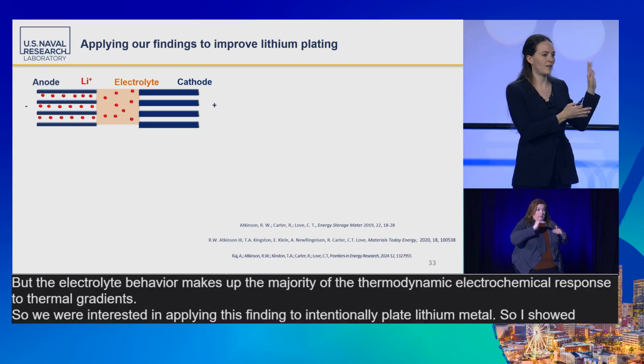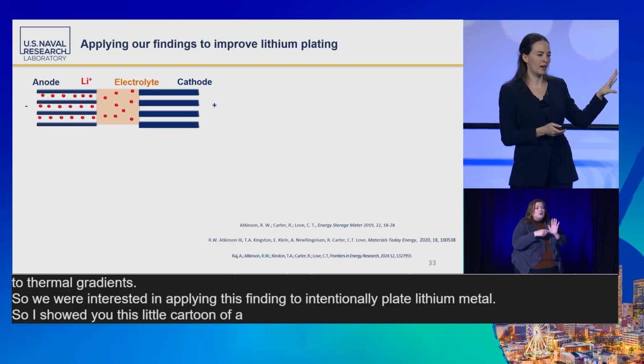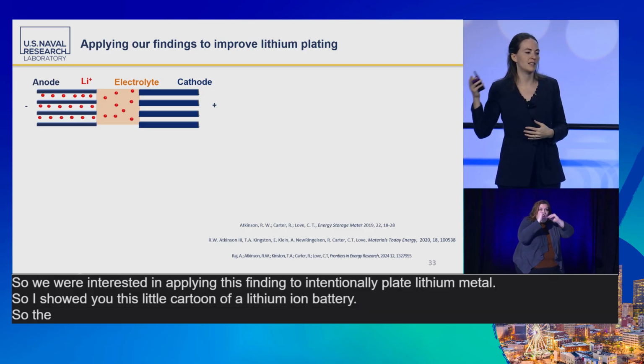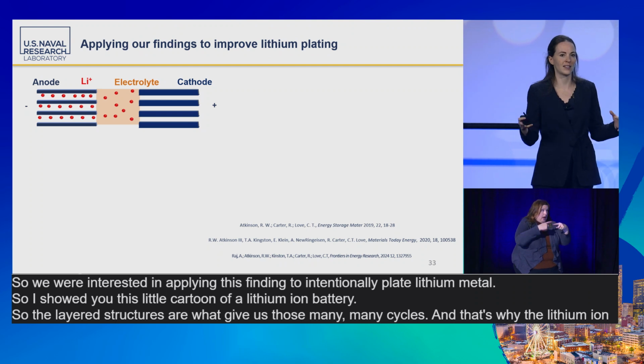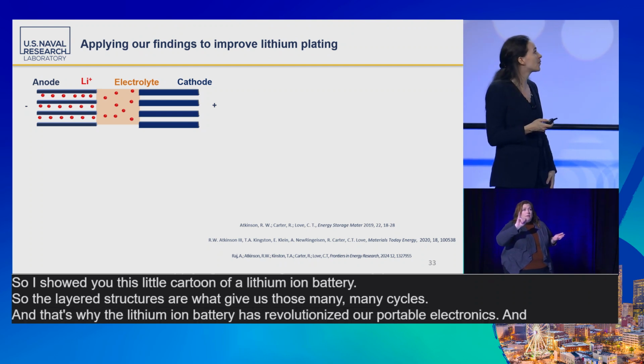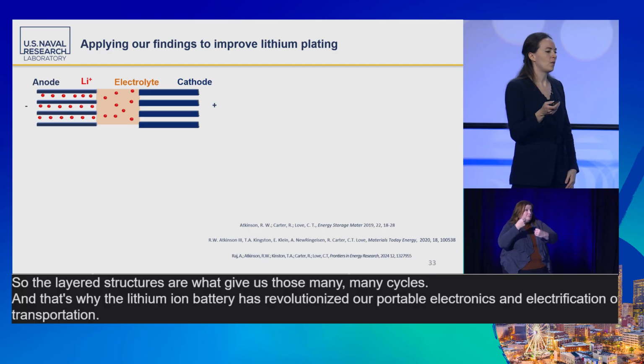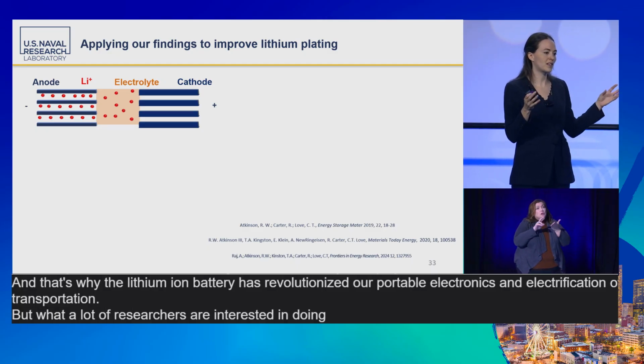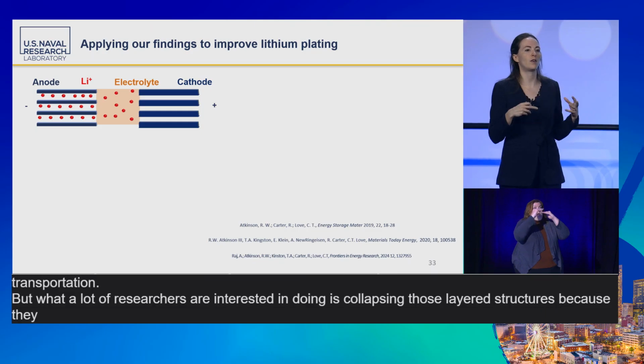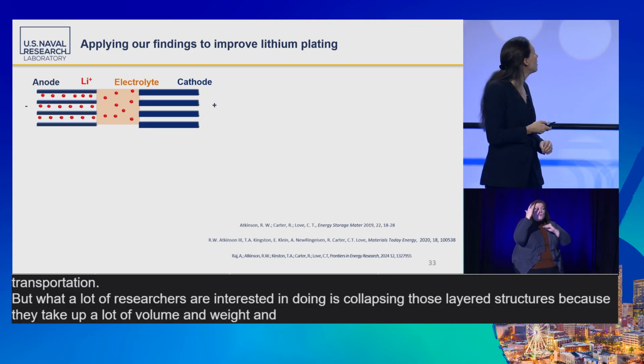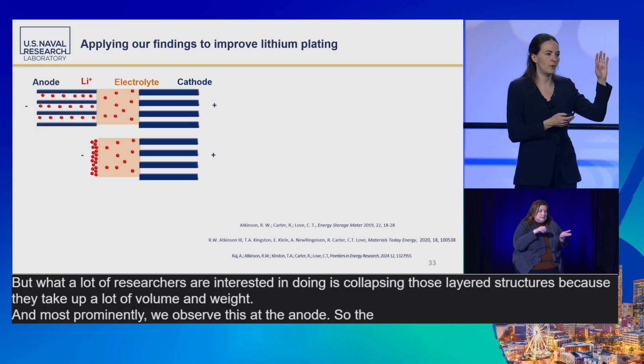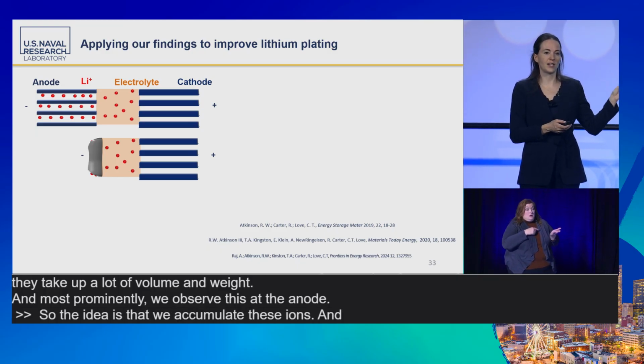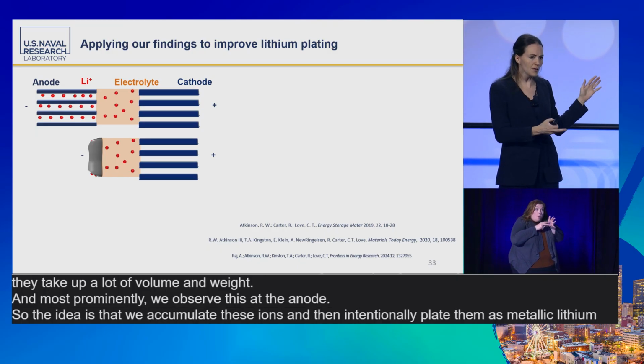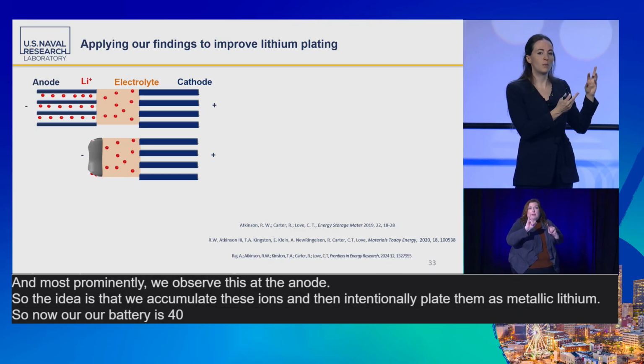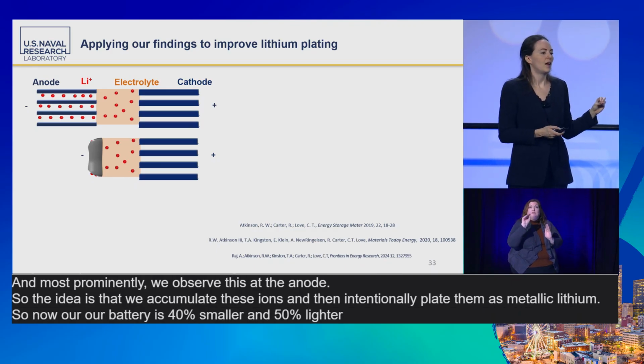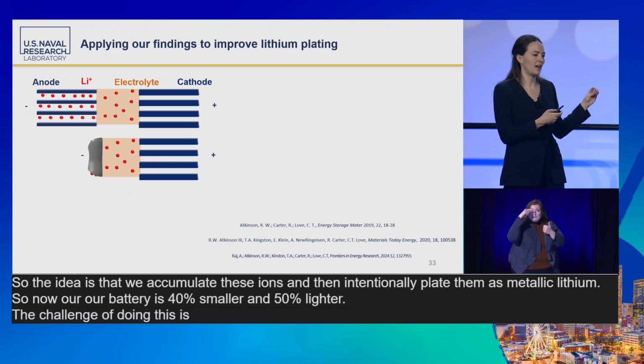So I showed you this little cartoon of a lithium-ion battery. So the layered structures are what give us those many, many cycles, and that's why the lithium-ion battery has revolutionized our portable electronics and electrification of transportation. But what a lot of researchers are interested in doing is collapsing those layered structures, because they take up a lot of volume and weight. And most prominently, we observe this at the anode. So the idea is that we accumulate these ions and then intentionally plate them as metallic lithium. So now our battery is 40% smaller and 50% lighter. The challenge of doing this is plating in an ideal morphology.